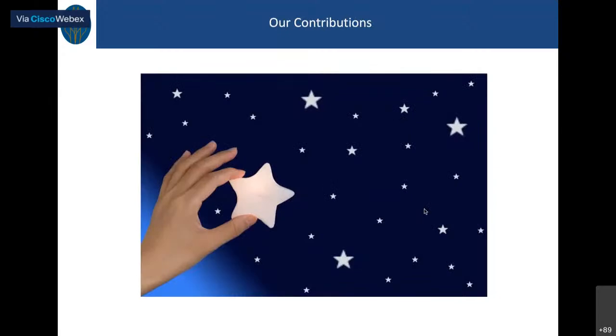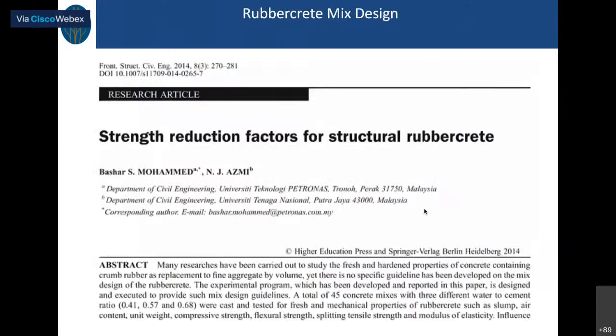Okay, this is just part of our contribution. The strength reduction factor is from some of the papers we published after we studied this rubbercrete: strength reduction factor for structural rubbercrete. When we add crumb rubber to the concrete, we call it rubbercrete, but we can't use the available standards to design the mix of this new concrete because of the material. So we have to develop a new procedure or method to design the mix of this rubbercrete.